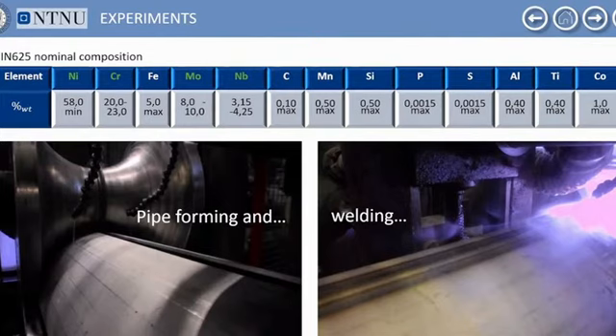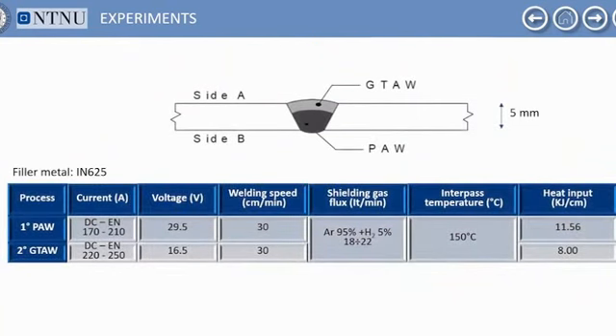These two pictures show the workpieces that we studied. There are pipes, tubes obtained by sheet forming and then welded using longitudinal welding. The longitudinal welding was performed with two runs, two passes. The first pass was carried out with a plasma arc welding, and the second pass was carried out using gas tungsten arc welding.